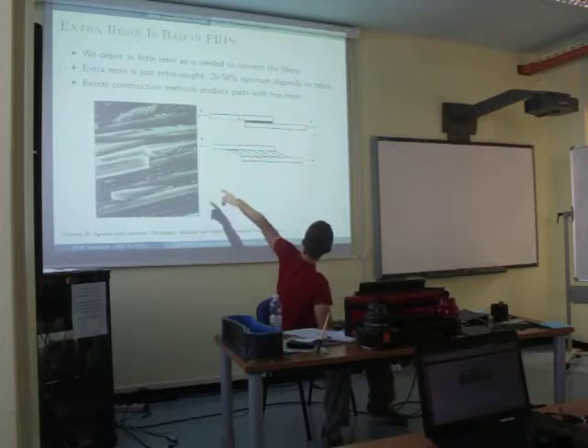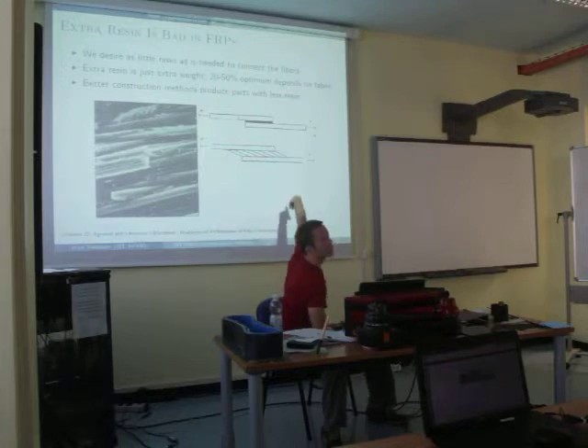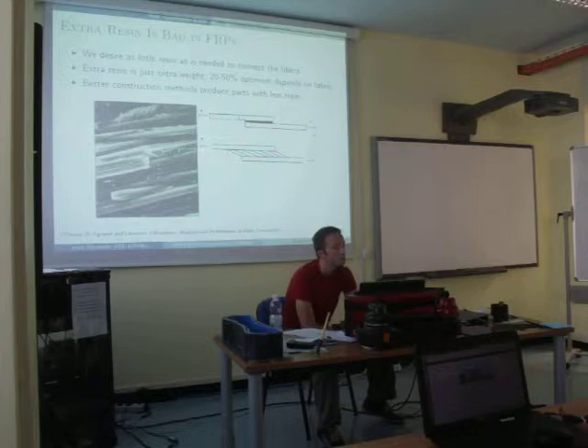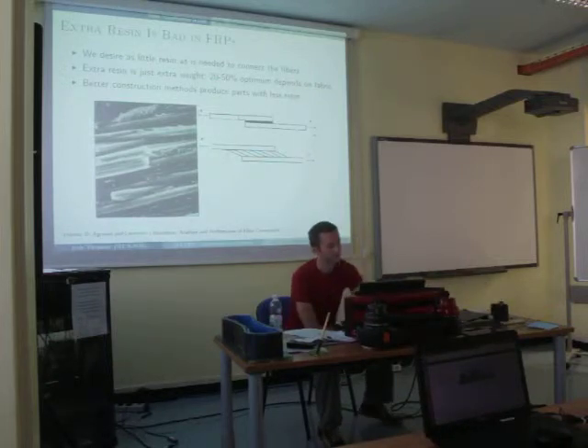So the closer these fibers are together, the stiffer the part's going to be because the resin matrix is more flexible. The weaker the part is going to be if you have extra resin, and the heavier it's going to be. So the better construction methods use autoclaves, high temperature ovens, a lot of pressure to squeeze out all the extra resin that they can. And depending on the type of fabric, that might be 20 to 50%. Unidirectional fibers usually use less resin than the bidirectional weave, the cloth weaves like this that we're going to use.